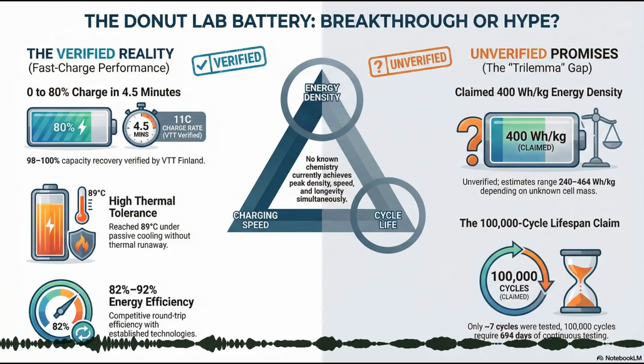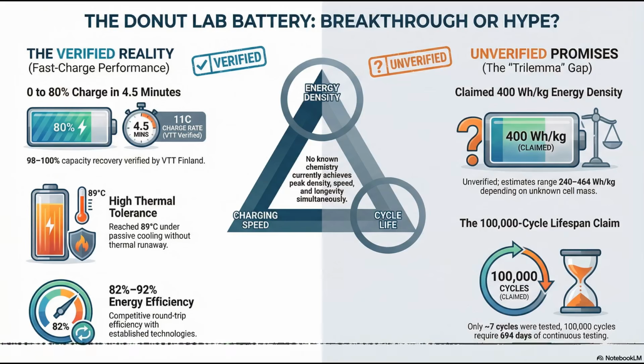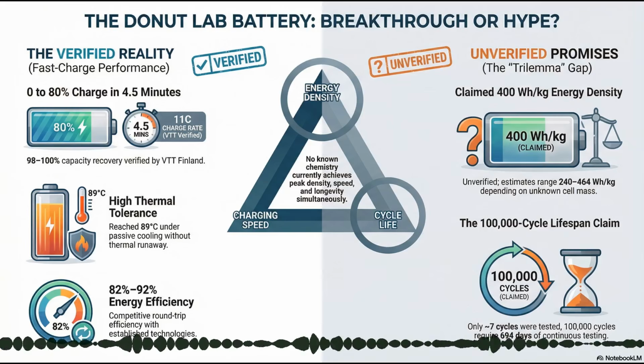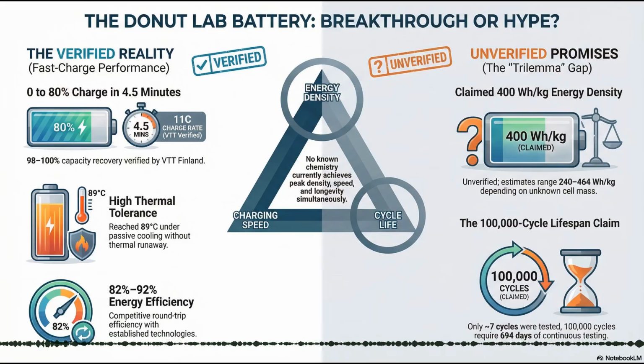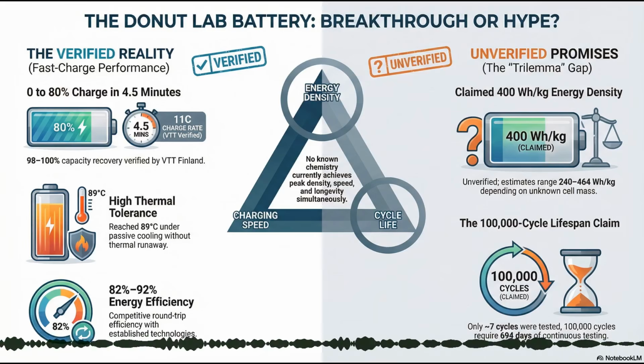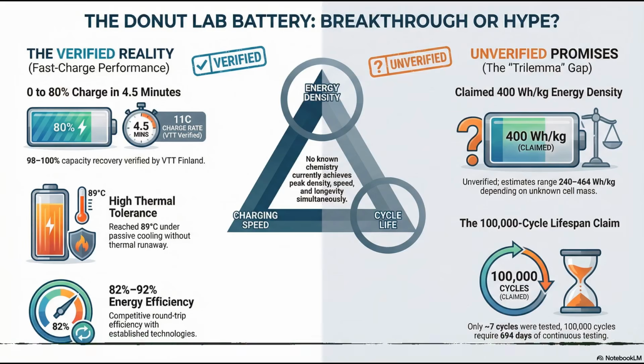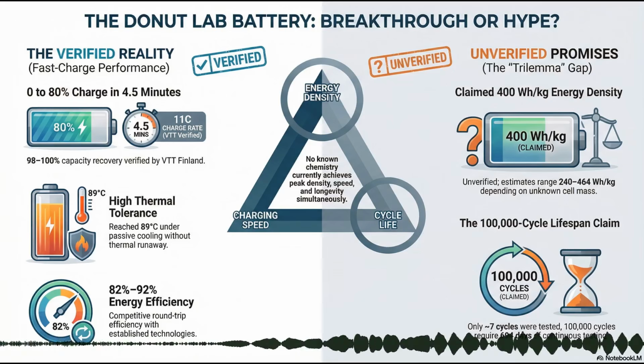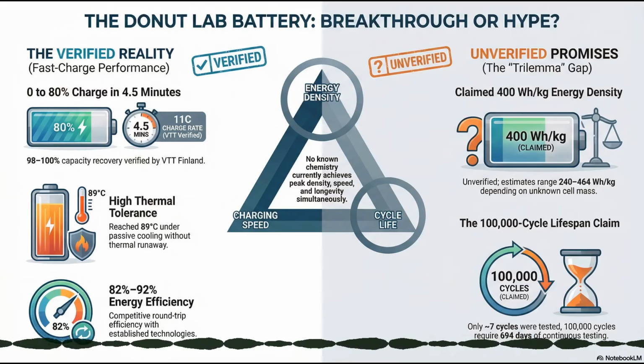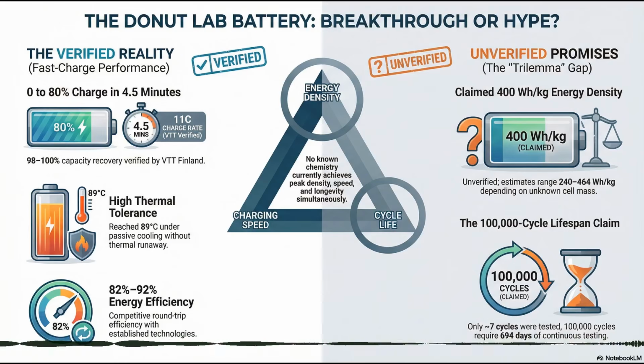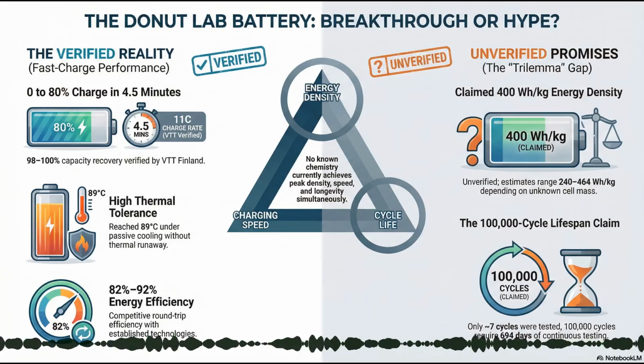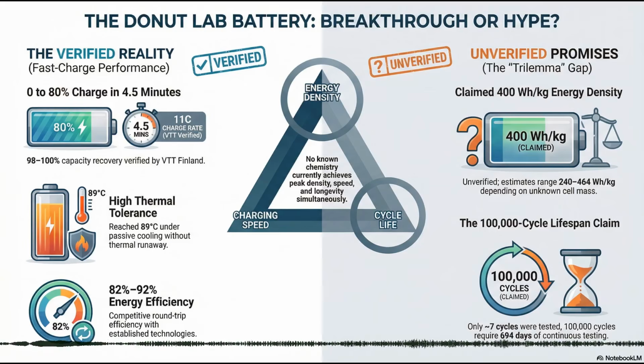If you get a standard NMC 811 liquid electrolyte cell to 90 degrees, you are entering the danger zone for catastrophic thermal runaway. The organic carbonate solvents start to vaporize and create internal gas pressure. The cell swells up like a balloon. Exactly. And the separator, which is usually a thin polyethylene or polypropylene film, starts to soften and lose its mechanical integrity. If that separator melts, the anode touches the cathode, you get a hard internal short, and the cell goes up in flames. But here, the cell survived.